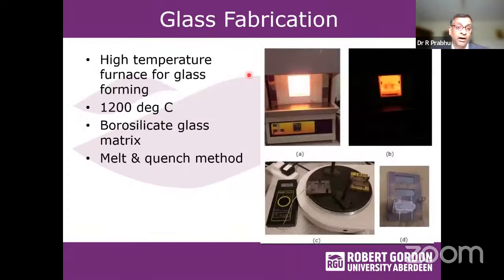So how do we manufacture, or how do we prepare the glass with rare earths in it? We have a set of high temperature glass furnaces, which can go up to 1,600 degrees. In this case, we selected borosilicate glass matrix as the base material, and we doped a set of rare earth elements into it. Since borosilicate glass is used, the temperature can be around 1,200 degrees. And we used the melt and quench method to fabricate the glass.